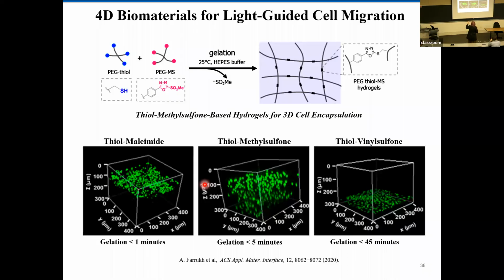In thiol-maleimide, when you put the cells in the hydrogel and you are trying to polymerize it, it polymerizes within less than a minute, which means it does not let you mix your cells properly and then let it polymerize. In the case of thiol-vinyl sulfone, it polymerizes really slowly. You have your hydrogel, you mix the cells on top, and then it takes 45 minutes to polymerize, which means that cells are going to settle down. And this is something you can see in the 3D stacks. In the first case, cells are just stuck on the top and there is nothing in the hydrogel. In the thiol-vinyl sulfone, the cross-linkage is so slow that everything has settled down.